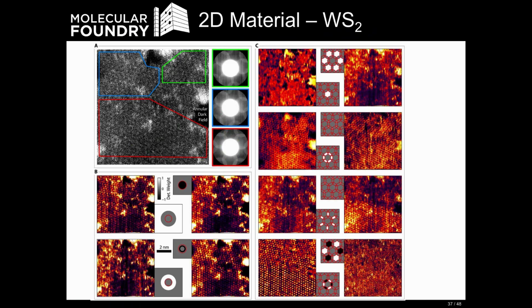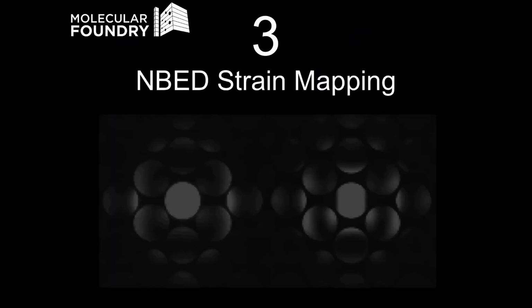But we can perform many, many different experiments after the fact. And this data set actually shows, too, that if you could measure where the disk positions are, you could also measure with extreme accuracy the local rotation of the lattice, or the orientation of it. You could look for grain boundaries. And if you could measure the disk positions with high enough fidelity, you could even map the local lattice vectors, so the strain of the sample. And that's what I'm going to show next here.